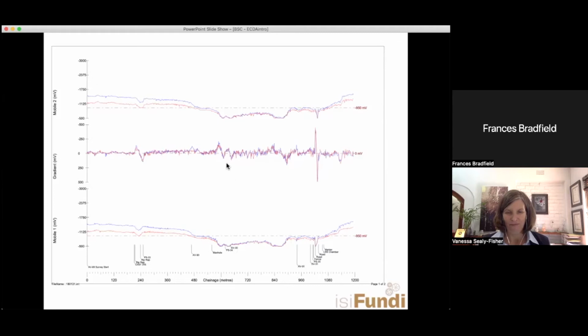I think that is probably somewhere around a road crossing, so that's even worse because we have an unknown in terms of soil resistivity and soil conditions, plus low potentials, meaning that our defects are unprotected. And so that's really one of the ones that would come up as a red, very concerned location. And then the final one is a very large defect, and it is also unprotected. So that would be 3 locations where we're a little bit concerned about what's happening there.